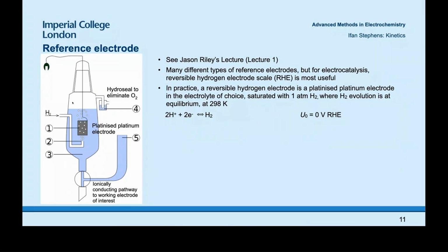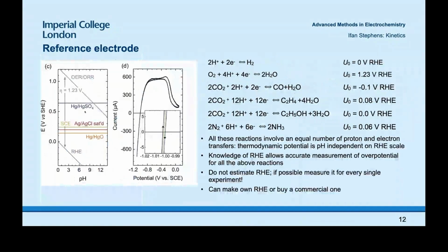The reason why this is a very, very convenient scale is if you look at a number of different reactions, including oxygen evolution and reduction, CO2 reduction to CO, CO2 reduction to ethylene or ethanol, or even nitrogen reduction, all these reactions often take place at a specific potential on the RHE scale, and this potential is pH independent. The reason for that is that you've got the same number of protons and electrons for each of these reactions. That means the thermodynamic potential for the reaction is pH independent on the RHE scale.